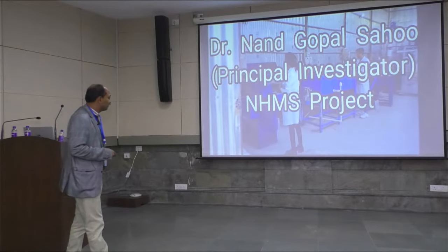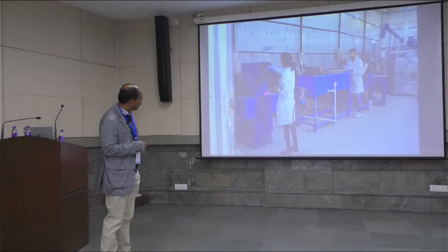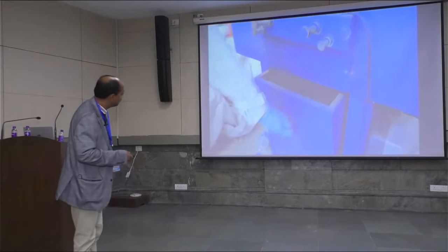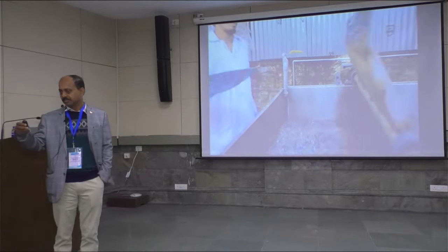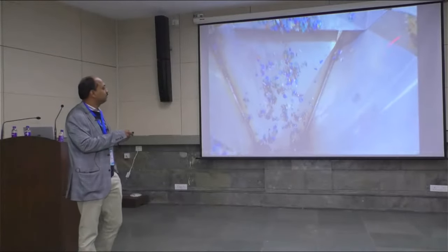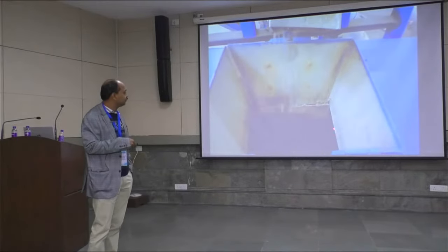This is actually for the demo. You can see the plastic bottles cut into very small pieces, 5 mm to 6 mm in size. After this comes washing, but nowadays we don't actually wash it. You can directly crush it and go to the mixing unit, where you can mix the plastics with catalyst.